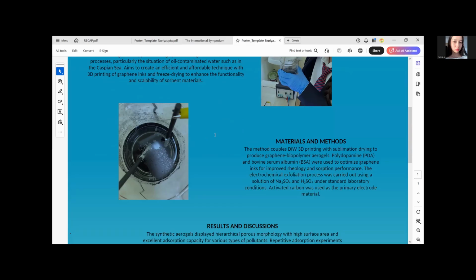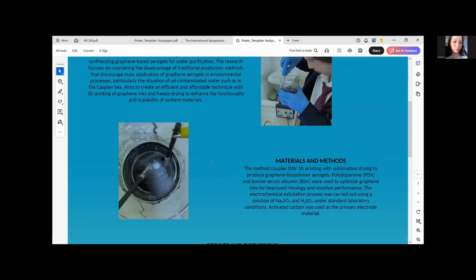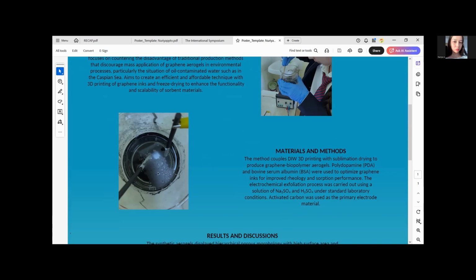So the method used the electrochemical exfoliation process with the use of sodium sulfate and sulfuric acid under standard laboratory conditions. And activated carbon was used as the primary electrode material. So on the screen here, you can see the process of electrochemical exfoliation, and on the surface, you can see graphene building up. These are graphene particles.